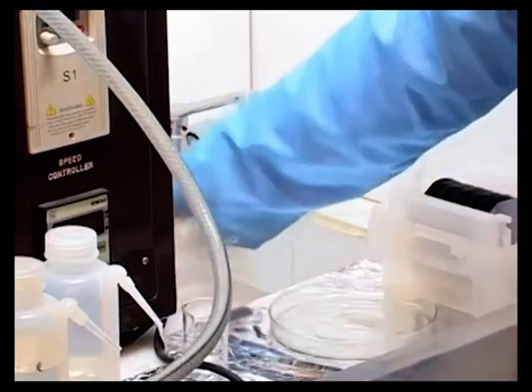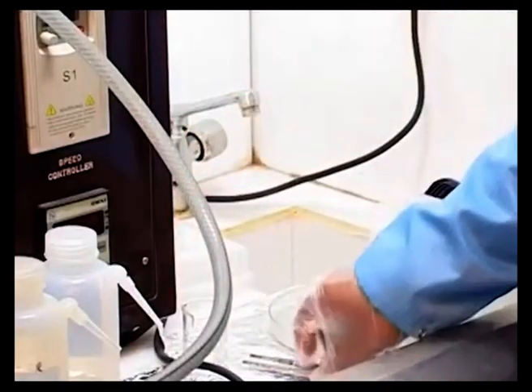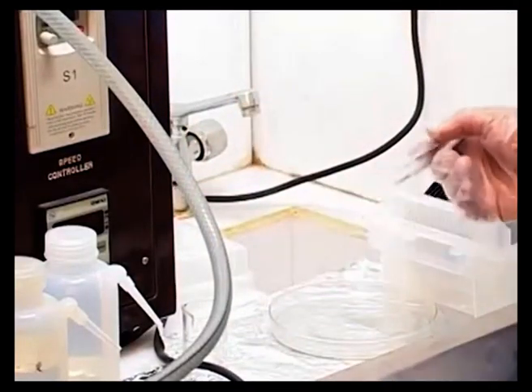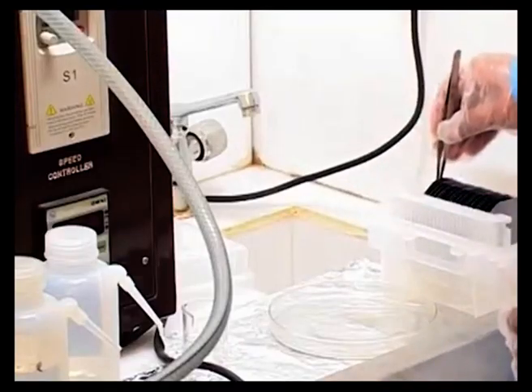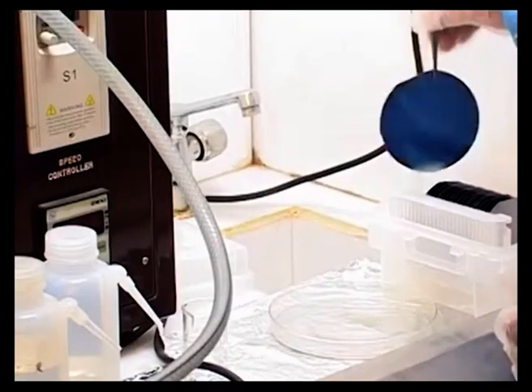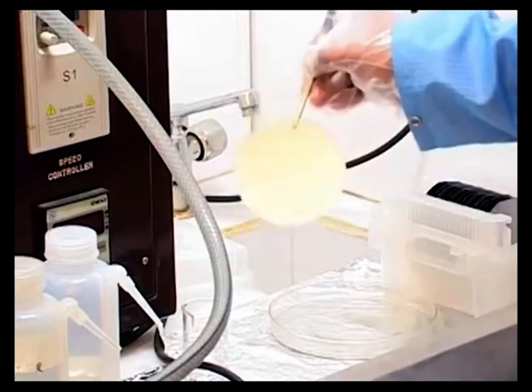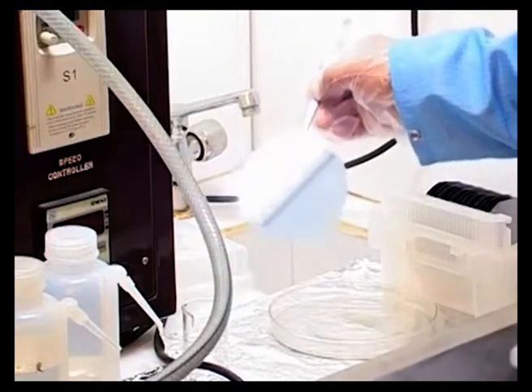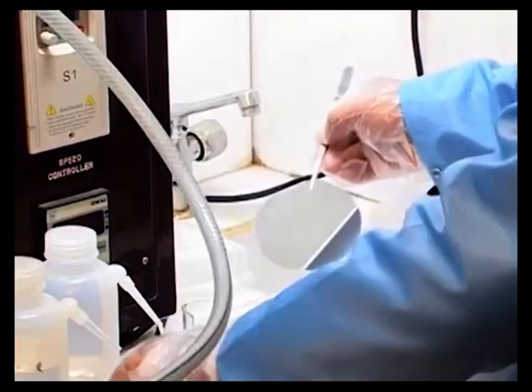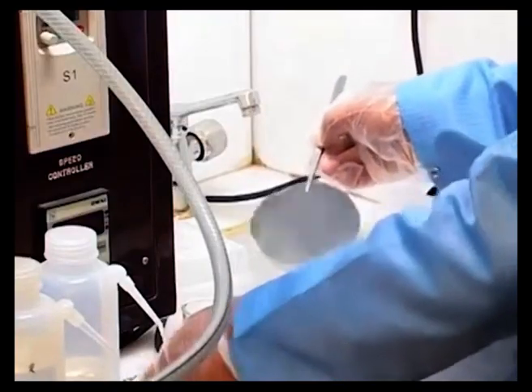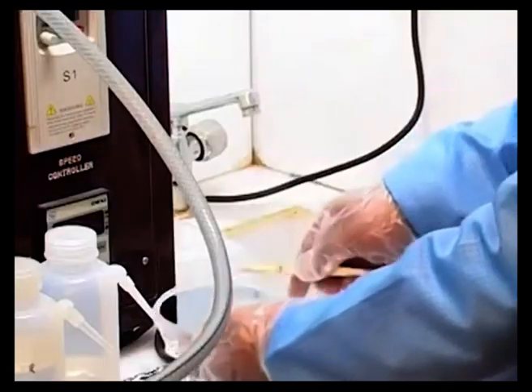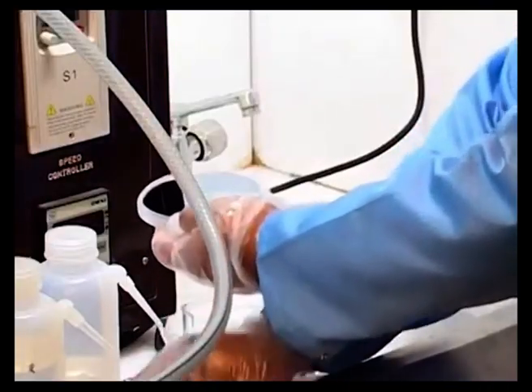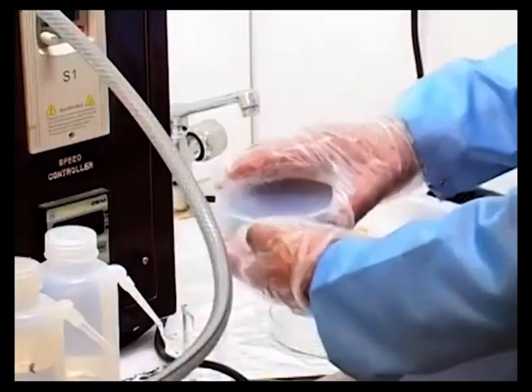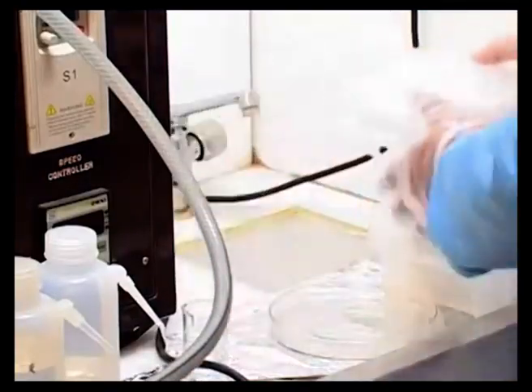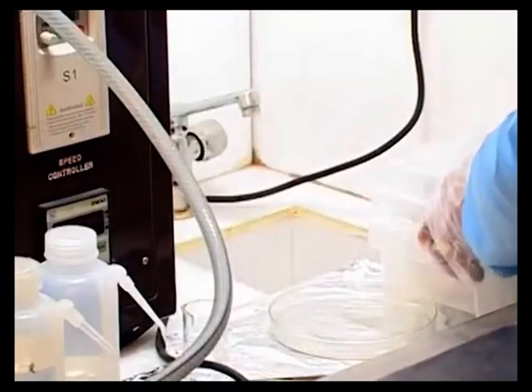This process only has to be done within a fume hood, because this prevents the chances of the wafer getting contaminated by the dust particles of the air. So we take a wafer out using a tweezer, as you can see here. Tweezer also is a very clean tweezer, and then essentially we use this box to load this wafer, and later on all the handling will be done using this particular box in the subsequent process steps, and then cover this with the lid. Okay. We close the silicon wafer box and keep it in a separate area.